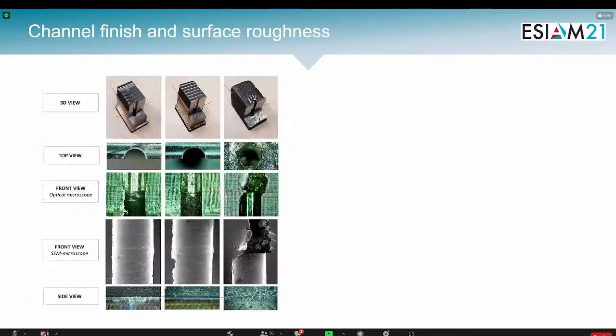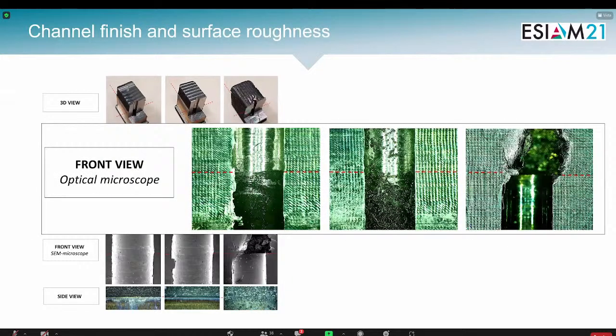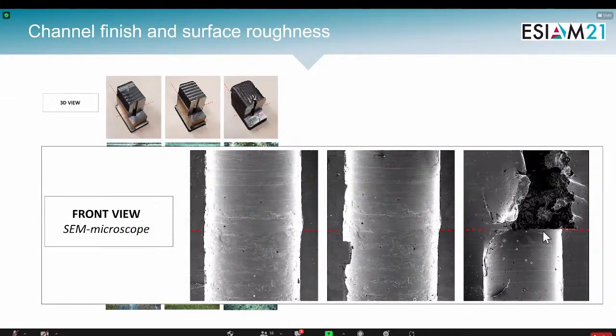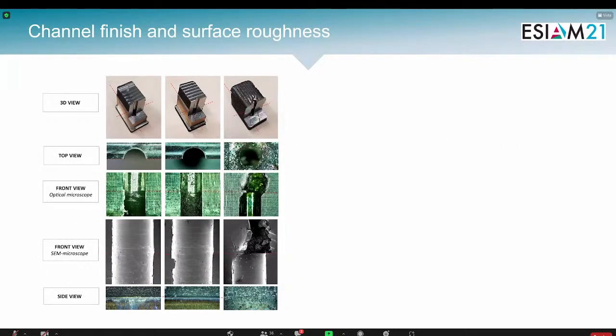And the aim of the study was also to evaluate, with SEM and optical microscope studies, the quality of the inner channel, because this is really important for the performance of this ESIAM system for the crack localization. So the presence of particles on the inner capillary can have a negative influence on the performance of the ESIAM system. So it was important to tune the parameters till reaching this finish. And as you can see, if you use the second strategy where you consider it in the print trajectory, you have a higher roughness due to these particles that stick on the capillary wall surface.